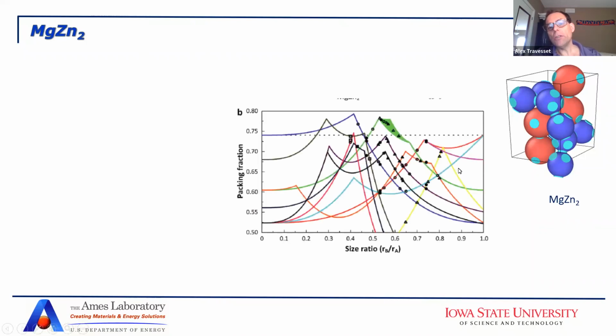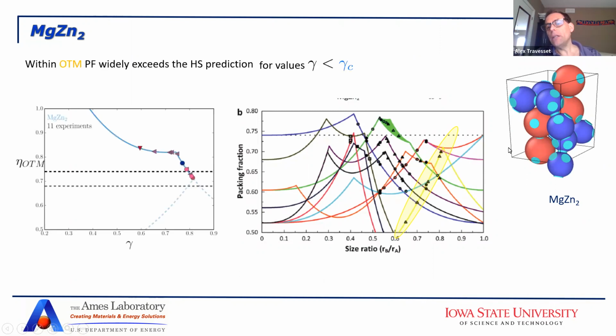So when you look at the packing fraction I already showed you and where the experiments are, what you realize is that if you deform the red spheres, then you will be able to increase the packing fraction in this particular branch, the left one, not the right one. And clearly this is very consistent with the experiments because you can see that the experiments are only on the left part. And that's because, as I mentioned, those are the only ones that can create vortices. And that gives you a unique prediction in which the hard sphere branch actually is lifted, and you can have a much higher prediction. And this is what the OTM predicts for the hard sphere of this case.